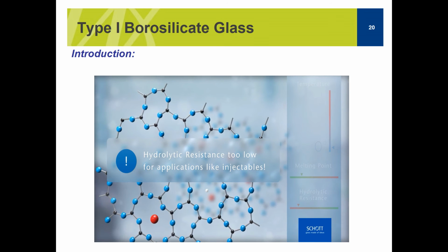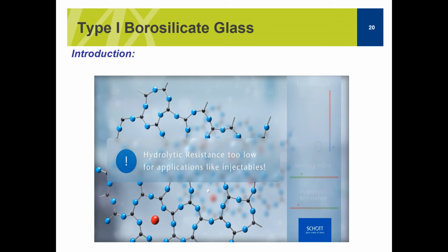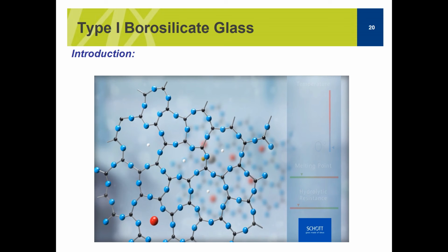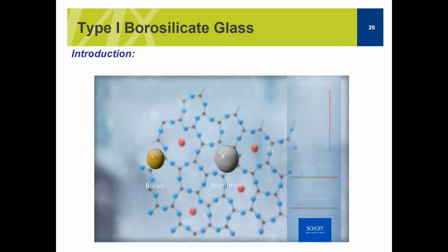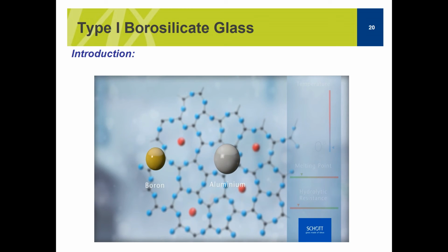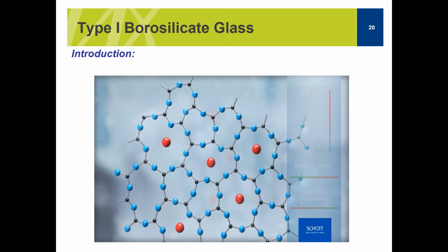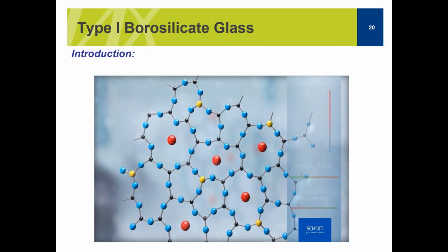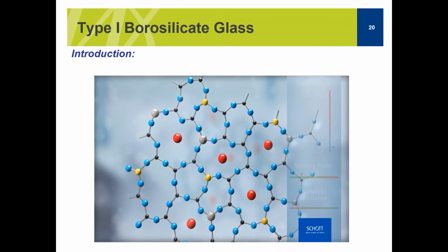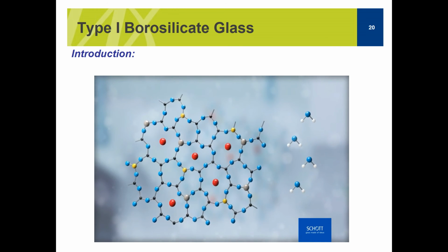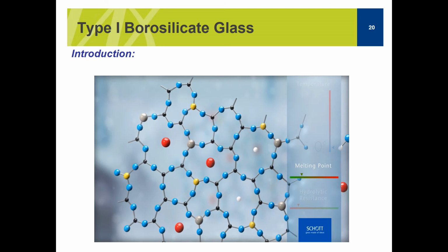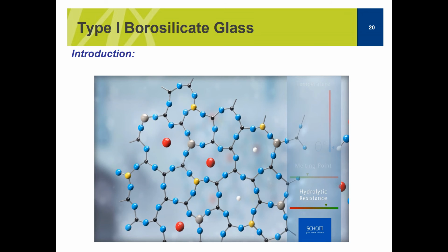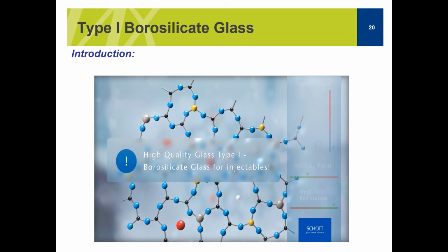For specific pharmaceutical applications, like solutions that are injected into the body, a certain minimum hydrolytic resistance is required. Thus, to re-strengthen the glass, boron and aluminum are added. They are integrated into the network and increase the resistance against water attack. Now, fewer network modifiers are exchanged for hydrogen. The melting temperature is increased a bit, but the hydrolytic resistance is increased significantly. This is the typical structure of a borosilicate glass type 1, which can be used for injectables.